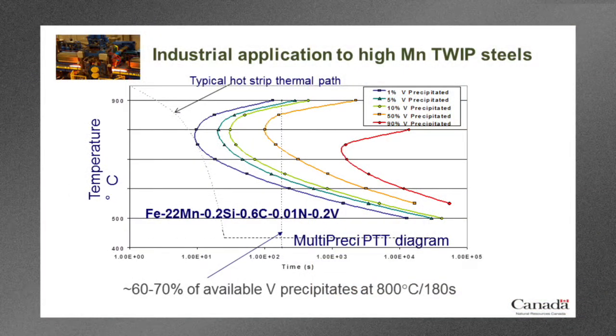Here is a kinetic precipitation diagram. This is calculated using the multi-Preci model, which was developed by Philippe Maugis and Mohamed Gouné at ArcelorMittal. And what it shows you is the PTT curves, precipitation time temperature curves, for this alloy here, iron 22 manganese, 0.2 silicon, 0.6 carbon, with 100 ppm of nitrogen and 0.2 weight% of vanadium. Now, superimposed on the diagram, there are two dotted lines. I hope you can see them.